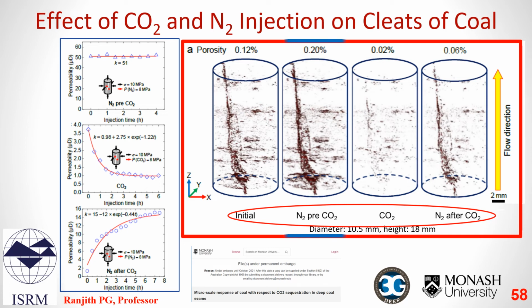After nitrogen injection, cleats opened from their initial confined condition. This is because the decrease of effective stress after gas injection tended to mechanically open the cleats. However, the cleats narrowed down and even closed after injecting carbon dioxide due to the coal matrix swelling accompanying CO2 absorption. After re-injecting nitrogen, the cleats open up again and the cleat porosity rebounded to 50% of the initial conditions.